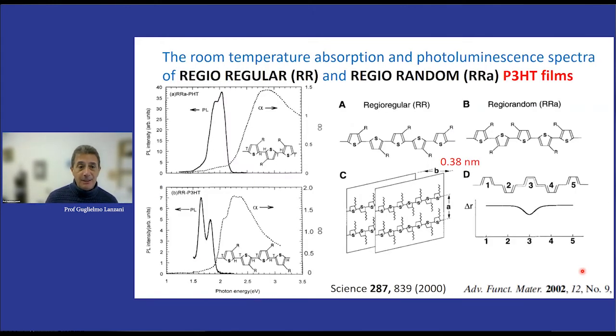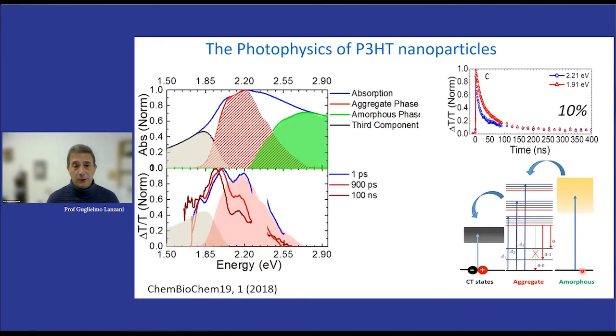Now, let me start this. In the nanoparticle, there is a combination of two different morphologies. There is an amorphous morphology of the polymer, which is absorbing higher energy, and there is a crystalline morphology, which is absorbing lower energy, and this is the fitting of the absorption spectrum. Most of the time, when we look at nanoparticles, we need to add a tail of states to reproduce the absorption. It is not fully explained, but I think it is due to the surface and the presence of charge transfer states, where the modulation of the transition energy due to the interaction with the environment is stronger at the surface.